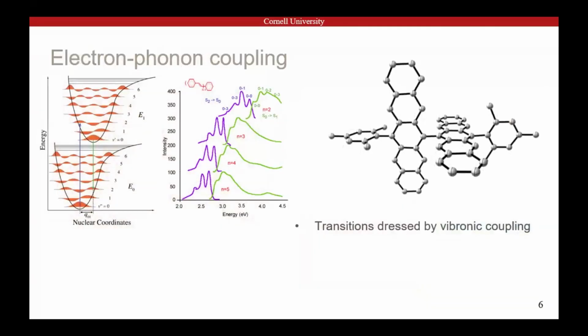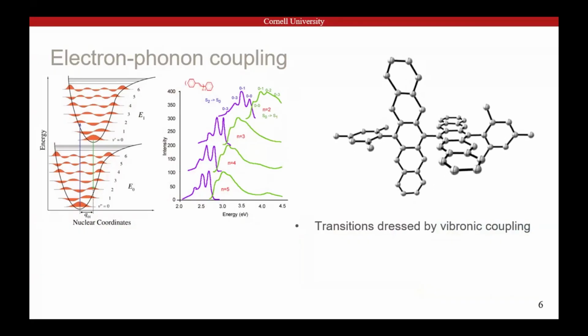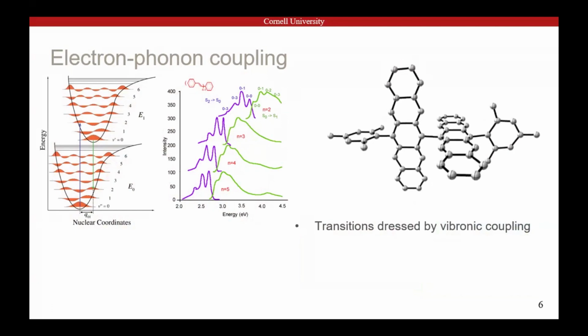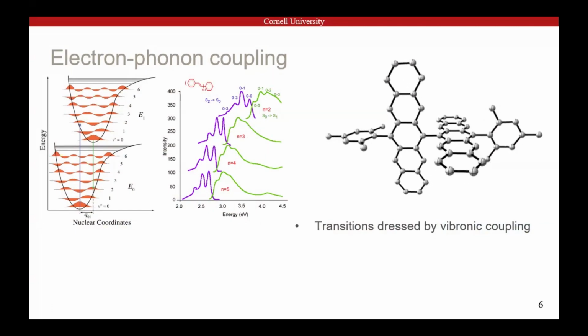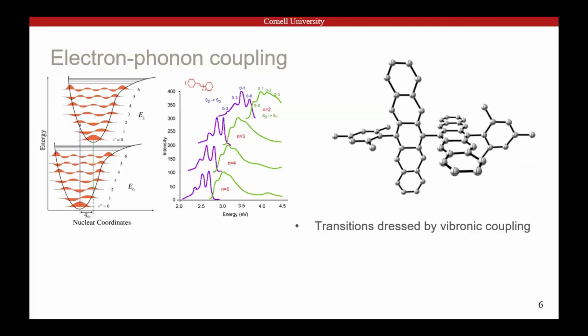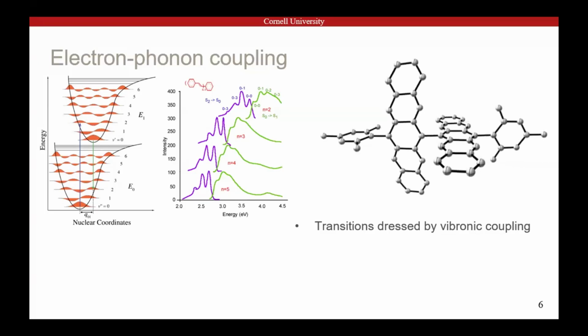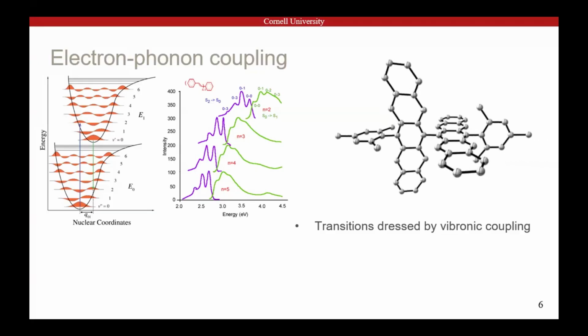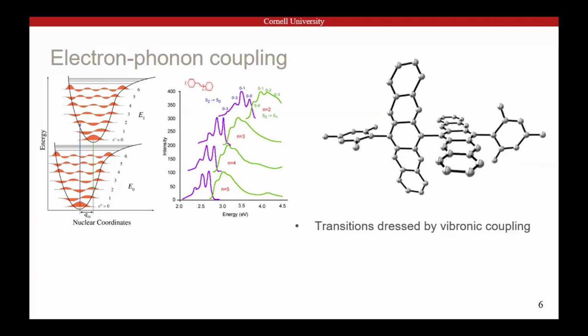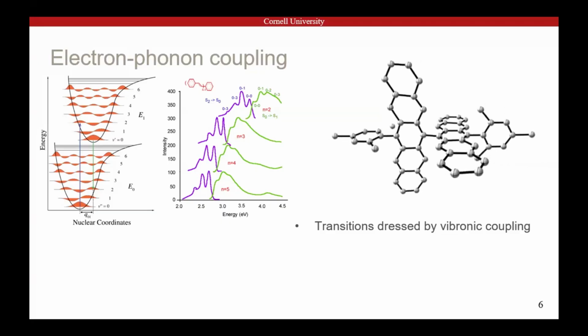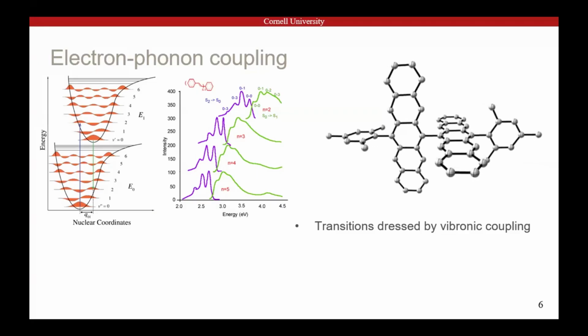The other thing that comes with working with molecular materials is their very unique electron-phonon coupling. And this is one of the defining characteristics of organic semiconductors. So we can have electronic excitations to generate these excited states, but these soft materials often also have a huge number of vibrational modes, localized phonons, if you will. And we can reconcile these motions with a really simple potential energy diagram, where you can photoexcite electronically and simultaneously excite certain numbers of quanta of vibrational excitation. And we know what this looks like in practice. You get absorption and emission transitions that are just dressed by these additional packets of vibrational energy.